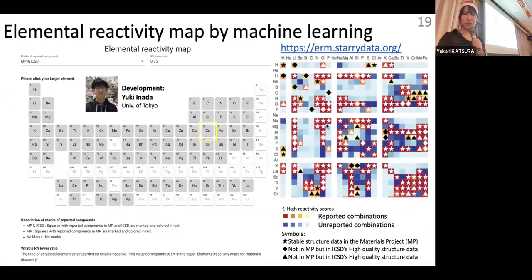So here is our map. The reported combinations are shown in red and yellow colors, and the predicted values of reactivity scores are shown in the darker colors. For the unreported combinations, we are showing in blue, and the dark blue regions were expected to be promising. You can access these maps from this URL, and if you select one element, then you can see the ternary map containing that element.